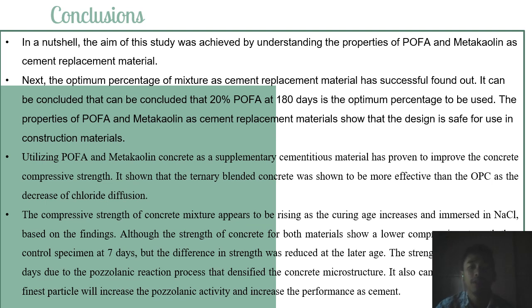Utilizing POFA and metakaolin concrete as a supplementary cementitious material has proved to improve concrete compressive strength. The compressive strength of the concrete mixture appears to rise with curing age, despite the immersion in sodium chloride. Based on the findings, the strength of concrete for both materials shows lower compressive strength than the control specimen at 7 days, but the difference in strength was reduced at later ages. The strength increased after 28 days due to the pozzolanic reaction process that densified the concrete microstructure. It can also be concluded that fine particles will increase the pozzolanic activity and improve performance as cement.